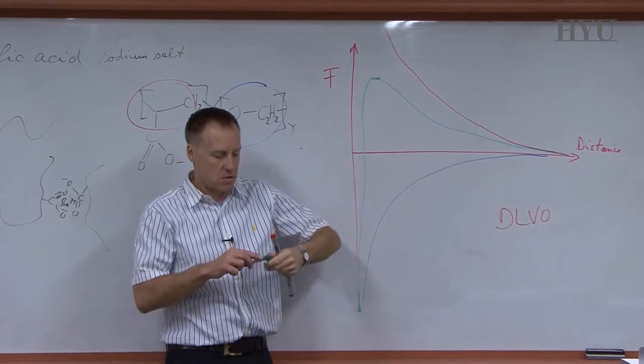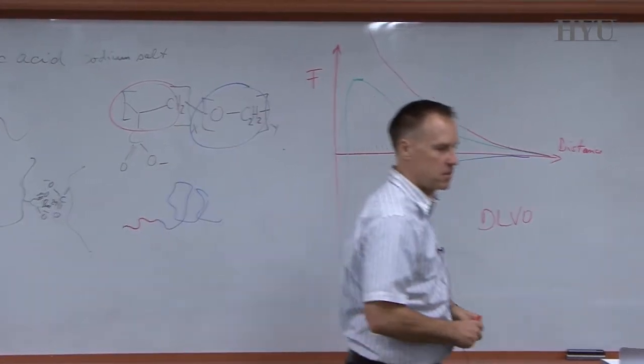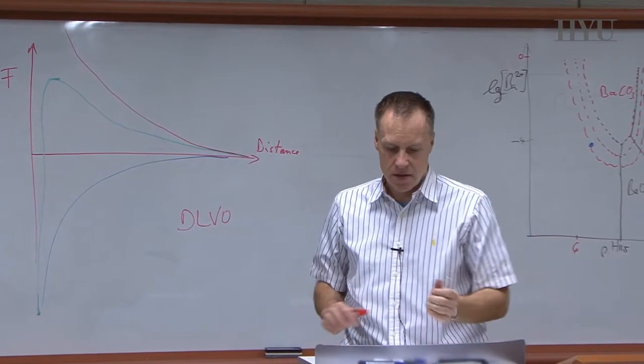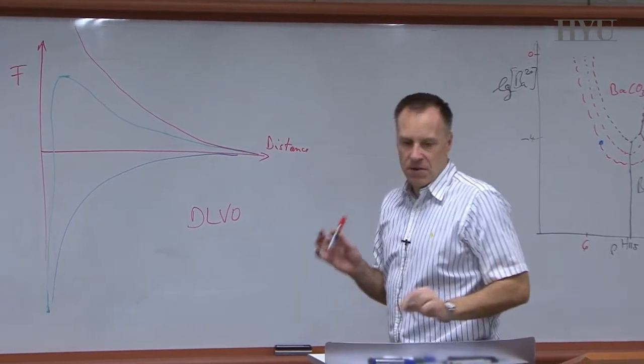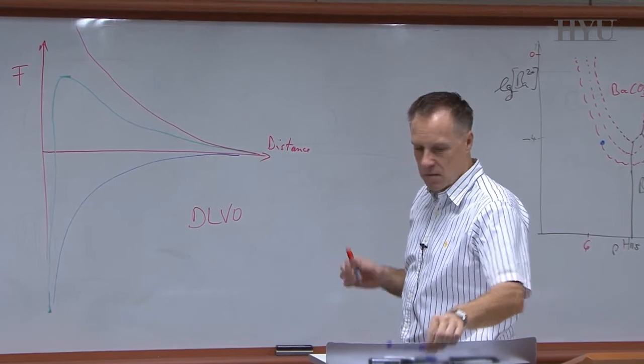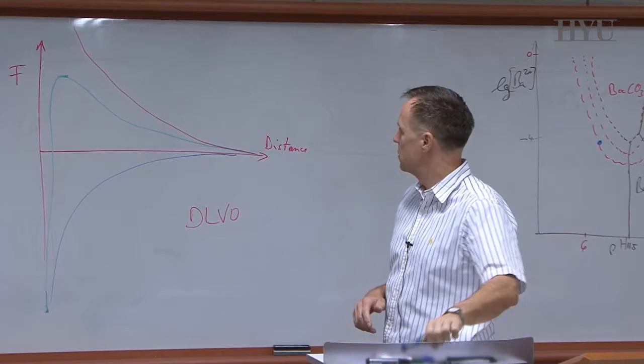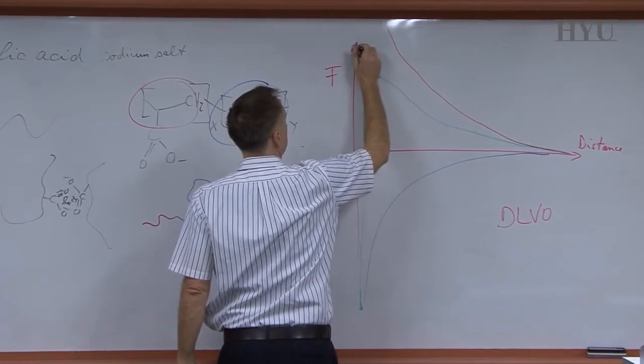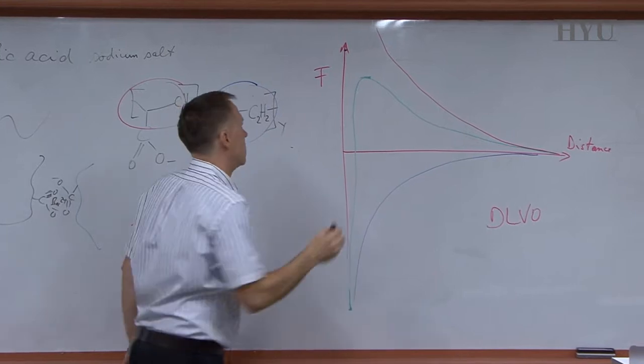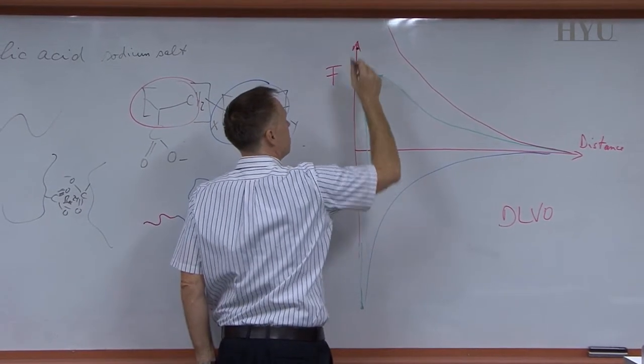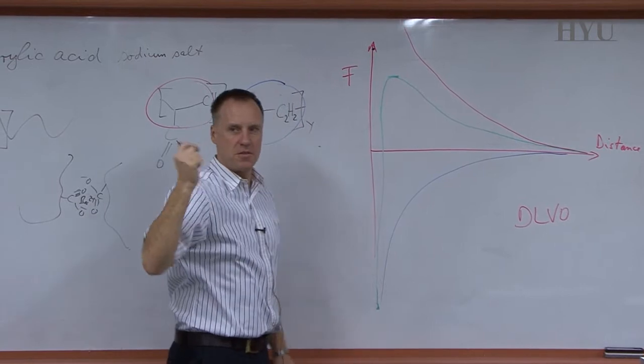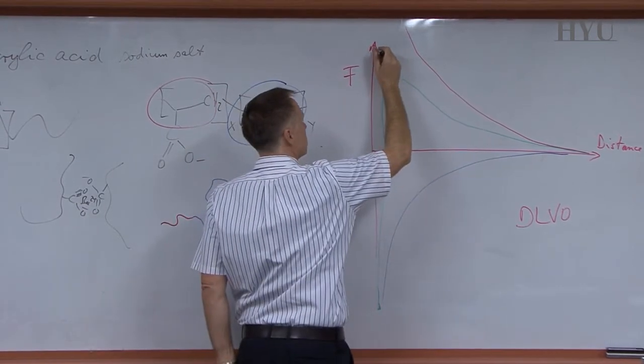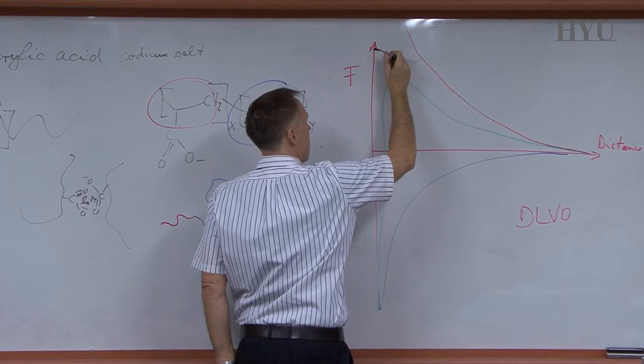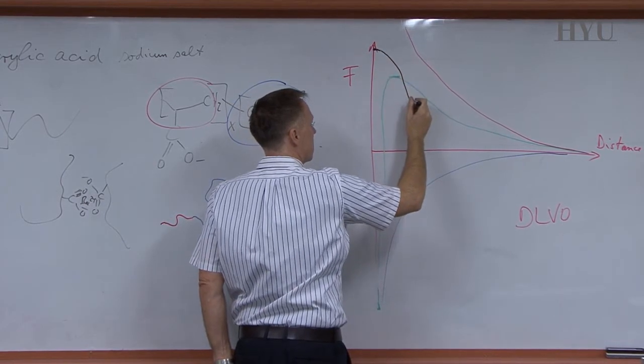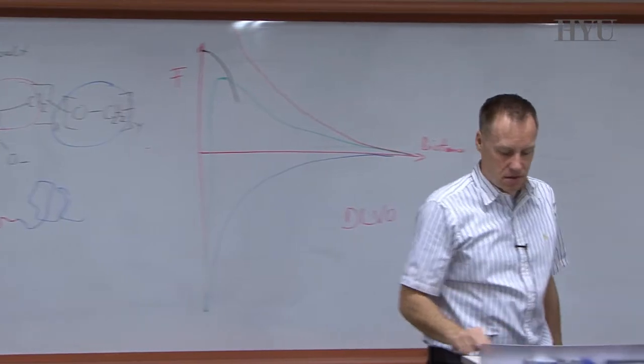Yeah? So what is the big difference now if you use polymers? Polymers are very, very different in this behavior, because once you adsorb polymers, let's use black, they are stuck here on the surface, and they give you a maximum repulsive force, but it's there. And the force is especially present when you're directly on the surface. Then another thing happens. As you move out, it drops. Let me see that to make it correct.